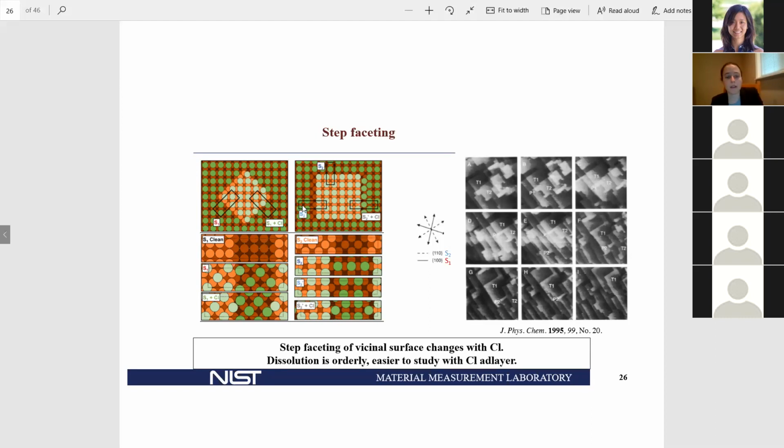chloride. However, the situation is a little more complicated in the presence of chloride because there are multiple possibilities for where the chloride can sit next to the step edge. There are S2 type steps where the chloride is relatively close to the step edge, but the S2 type step constrains the perpendicular S2 type step to an S2 prime step because, because of the way the lattice is structured, the chloride can no longer sit as close to the step edge. So we have S2 type steps and S2 prime steps, but we could also imagine putting a chloride in between on those sites, and that becomes the S2 prime plus chloride.